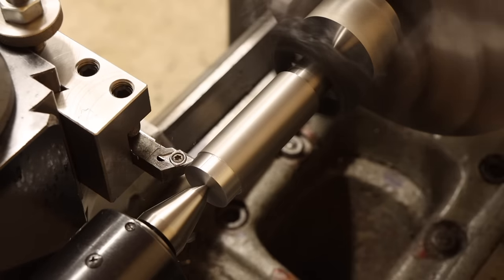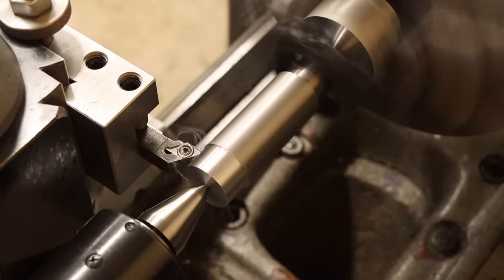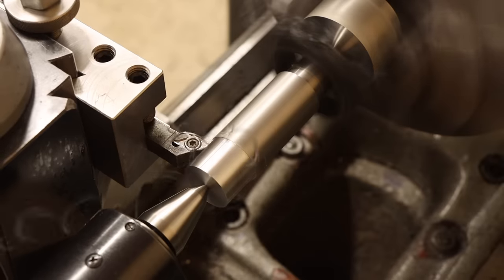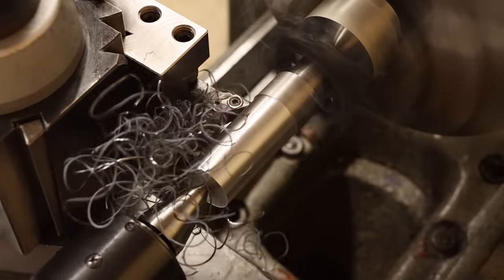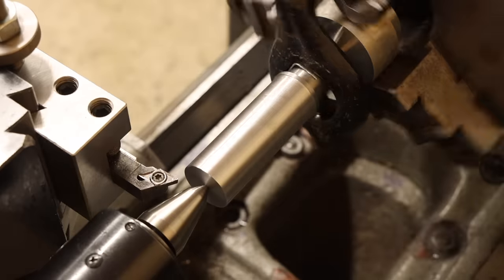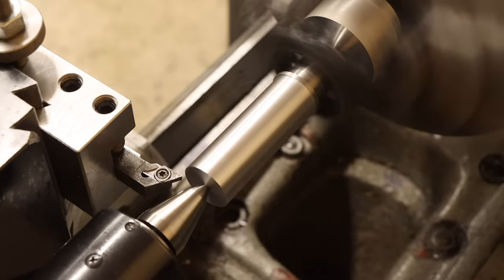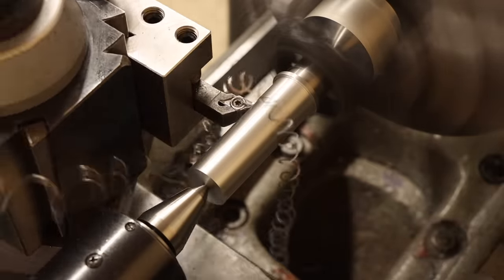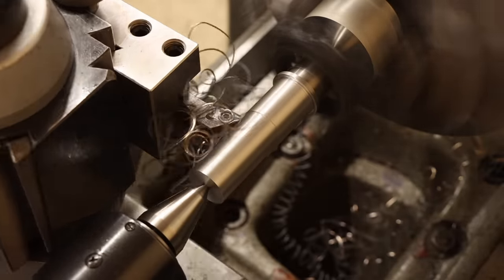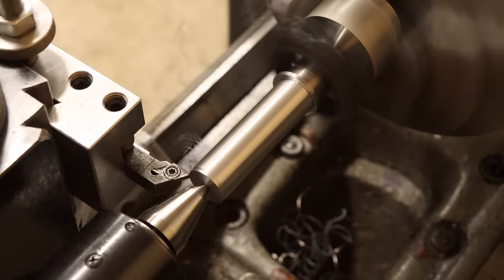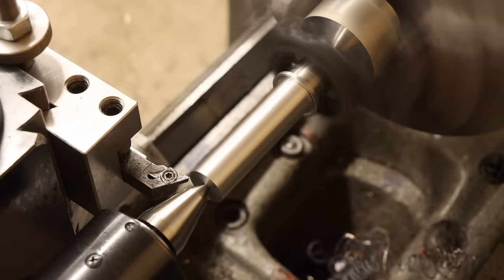The advantage of turning between centers like this is that it doesn't prevent the part from bending how it wants to as material is removed and internal stresses are relieved. Every small bend from each pass is straightened out by the following pass, where if this is held on the chuck and tailstock, the part wouldn't be allowed to bend. Those changes would accumulate after each pass, and as soon as you let the part go, that bending would happen all at once, making that forbidden banana nobody wants.